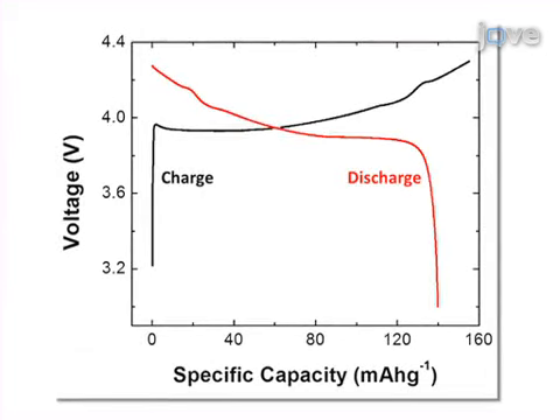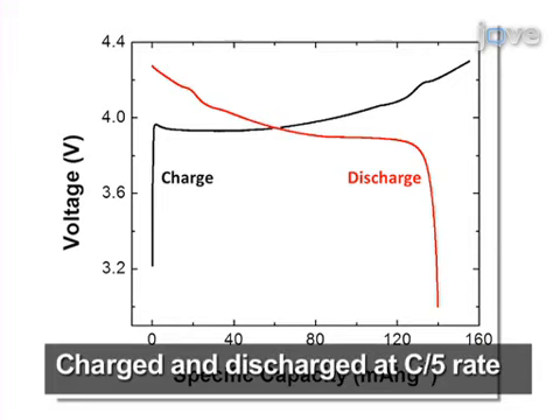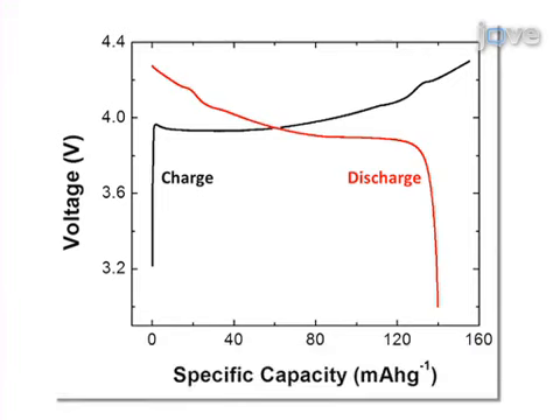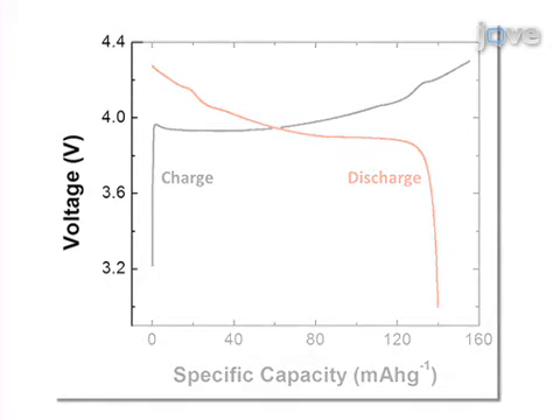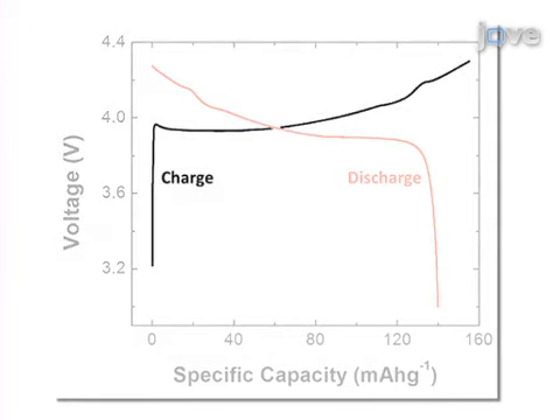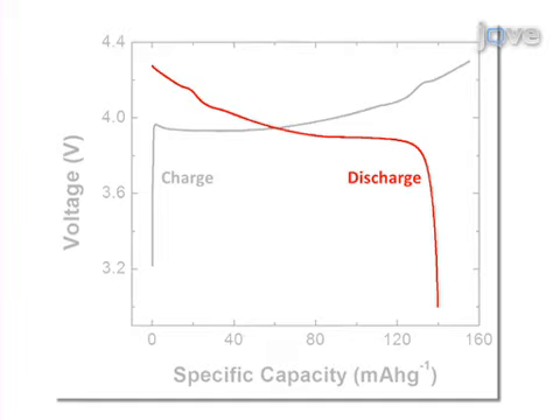These data are representative of a coin cell constructed from a working electrode of lithium cobalt oxide and a lithium foil counterelectrode. The plot shows the first charge and first discharge curves for the coin cell. Note, the voltage window was set to be between 3 and 4.3 volts. The capacity was 155 mA per gram for the first charge cycle and 140 mA per gram for the first discharge cycle.